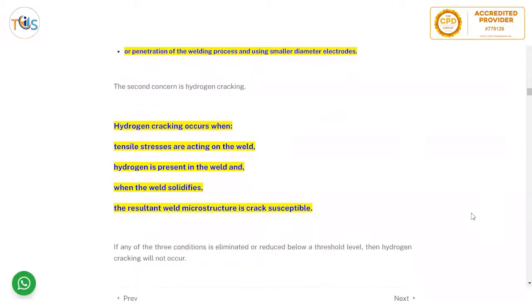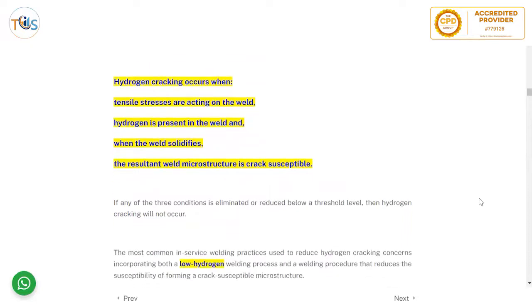Second concern is hydrogen cracking. Hydrogen cracking occurs when tensile stresses are acting on the weld, hydrogen is present in the weld, and when the weld solidifies, the resultant weld microstructure is crack susceptible. So there are three parameters for hydrogen cracking to happen. One is a tensile stress, one is presence of hydrogen, and then the resultant microstructure when the weld solidified, which could crack.